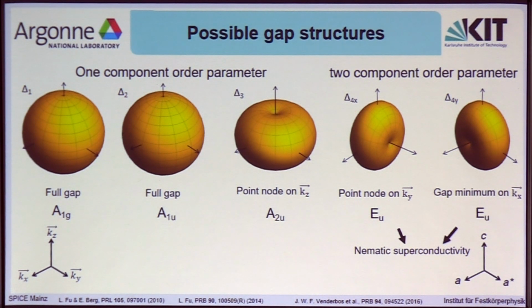There are several superconducting gaps that are possible for this trigonal system. There are the one-component order parameters that are labeled delta 1, delta 2, and delta 3. And there are the two-component ones, delta 4x and delta 4y, which are allowed for our system. Now, you can immediately see that delta 1, delta 2, and delta 3 do not have any in-plane anisotropy, so they couldn't be responsible for the twofold symmetry that we see. However, delta 4x and delta 4y have a clear twofold anisotropy in the plane, so they could very well explain our observations. How can we distinguish between those two?